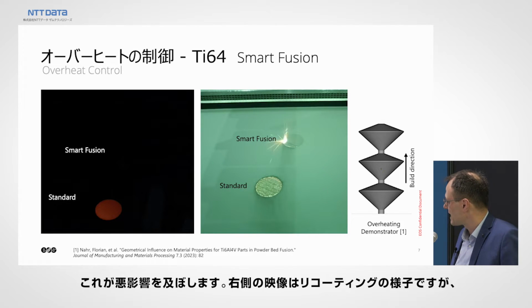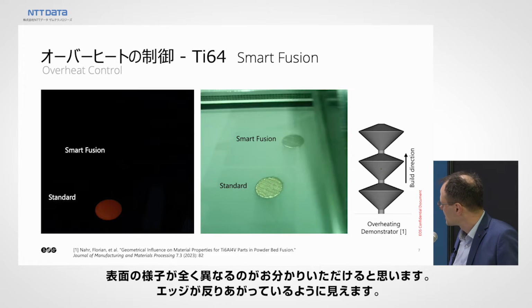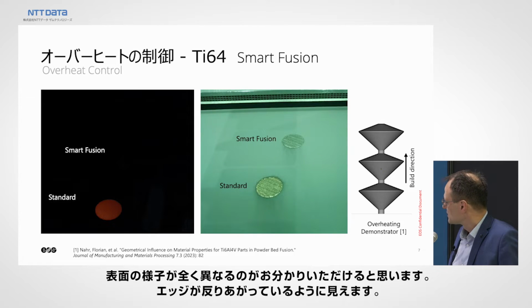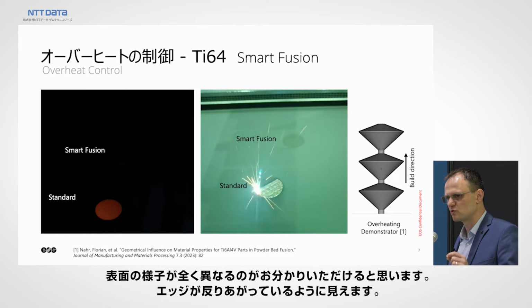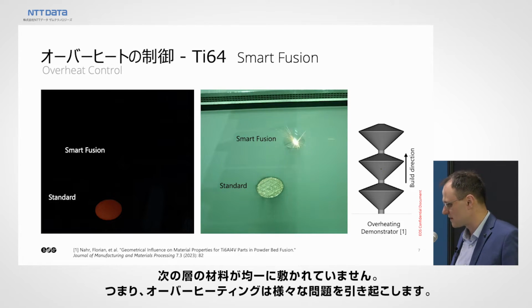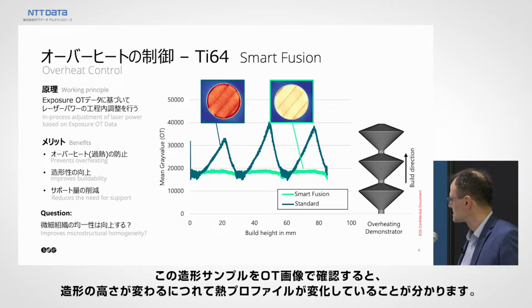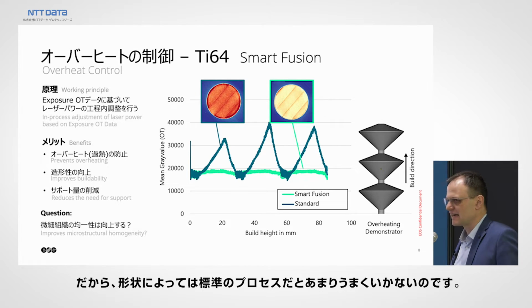You see that also in the recoating behavior of that sample here on the right-hand side. Sorry, why that doesn't work properly, but you can really see that this surface looks very different to this surface. So here you have edges that come up on the perimeter, and the contour is sticking up. The recoating after spreading a new layer doesn't look very even. So this is all leading to problems. And when we take this sample and we see that in the OT images, you can clearly see that with the changing height, the thermal profile is constantly changing. And this is exactly the problem, that a lot of the applications are not really successful with standard processes.